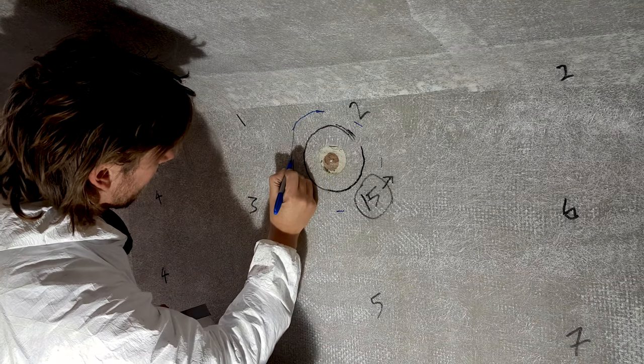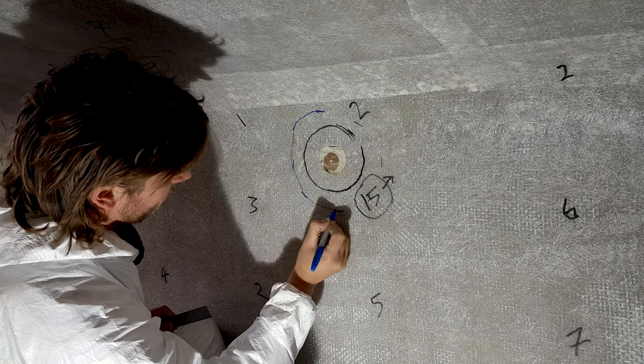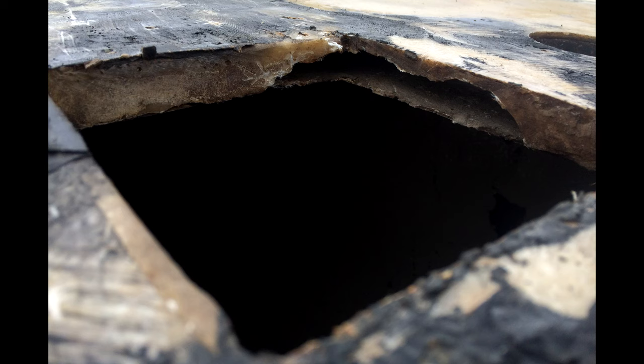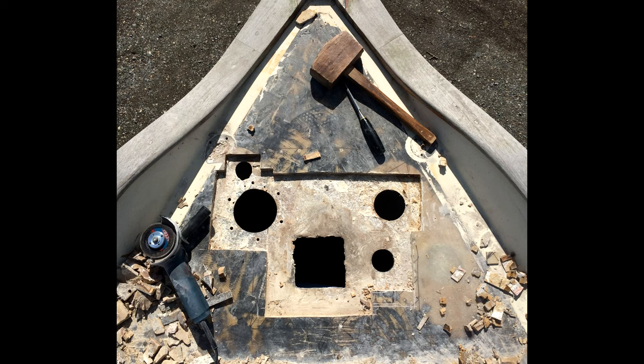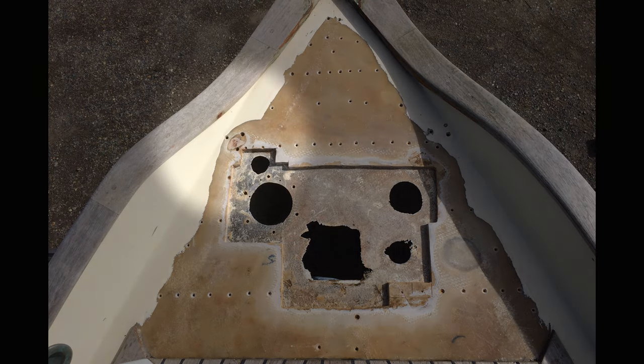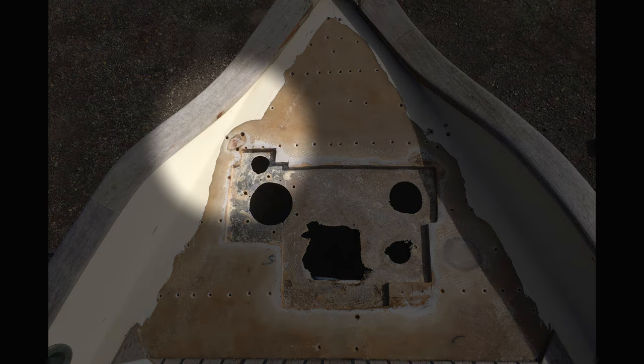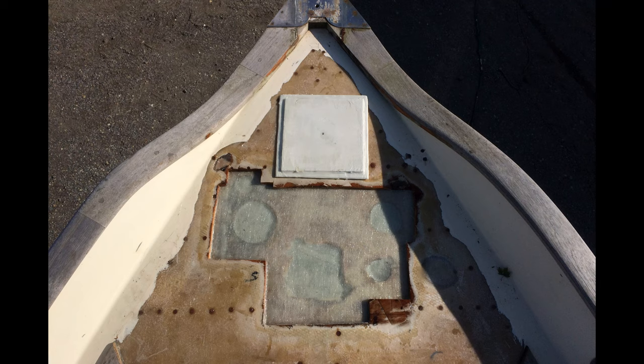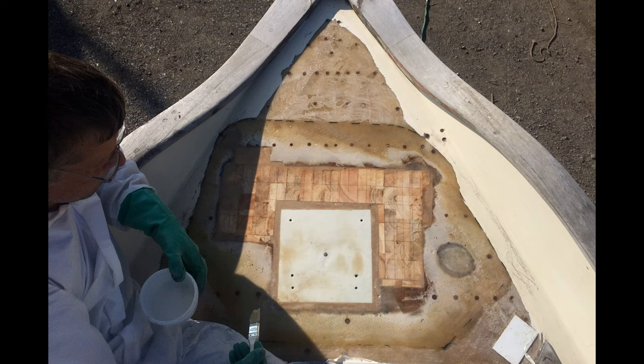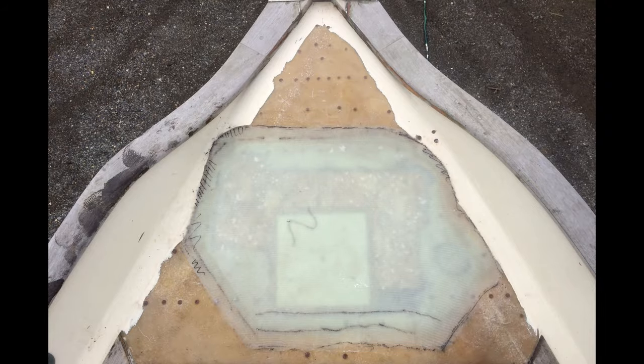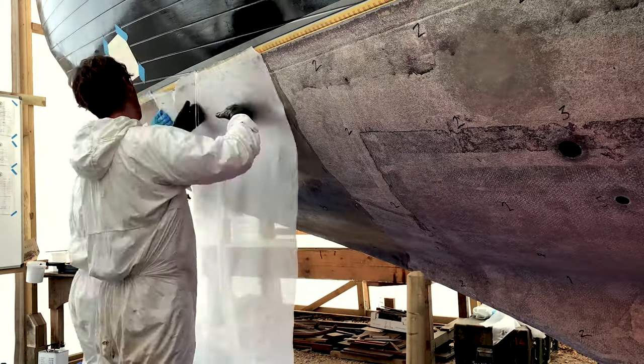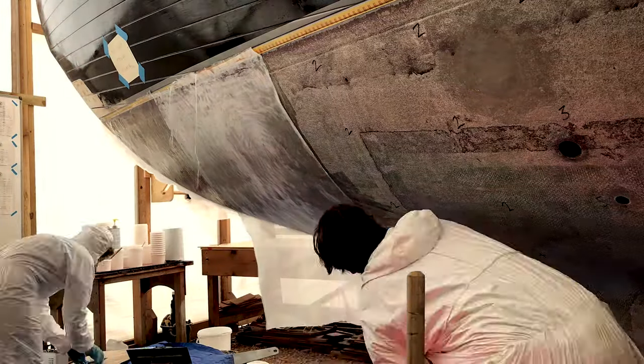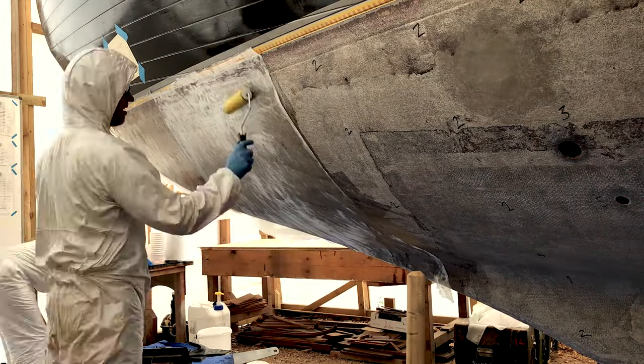Here we're on the side of Black Sheep and there's nothing stopping me having a scarf angle of 1 in 12. Here's where the Sampson posts went through the foredeck on Black Sheep. Once we'd removed all the rotten core material, we realized that the bulwarks prevented us from getting our nice 1 in 12 scarf gradient. To give us some extra strength because of this restriction, we did this whole repair in epoxy. So far we've spoken about the strength of these different resins, but there are other factors to consider.